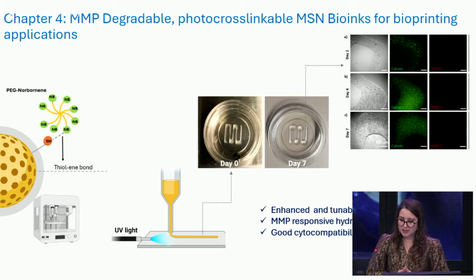Our degradation studies further confirm that these hydrogels can degrade over 24 days in the presence of MMP9 enzyme. And our bioink formulation, which included MG63 cells, solidified rapidly upon UV exposure and formed filament structures with good mechanical integrity. And importantly, in vitro studies confirmed that MG63 cells remain viable within the printed constructs up to 7 days.